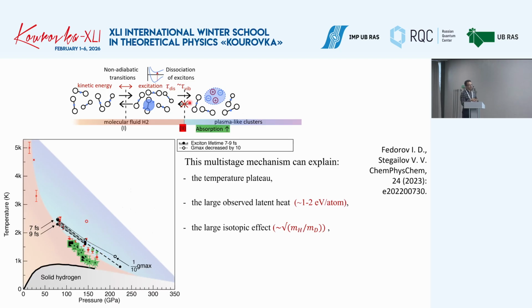And this picture gives a physical explanation to different observed phenomena connected with hydrogen, and the pressures and temperatures for this threshold mechanism agree quite nicely with the results of the diamond anvil cell measurements. That is very pleasant for us.